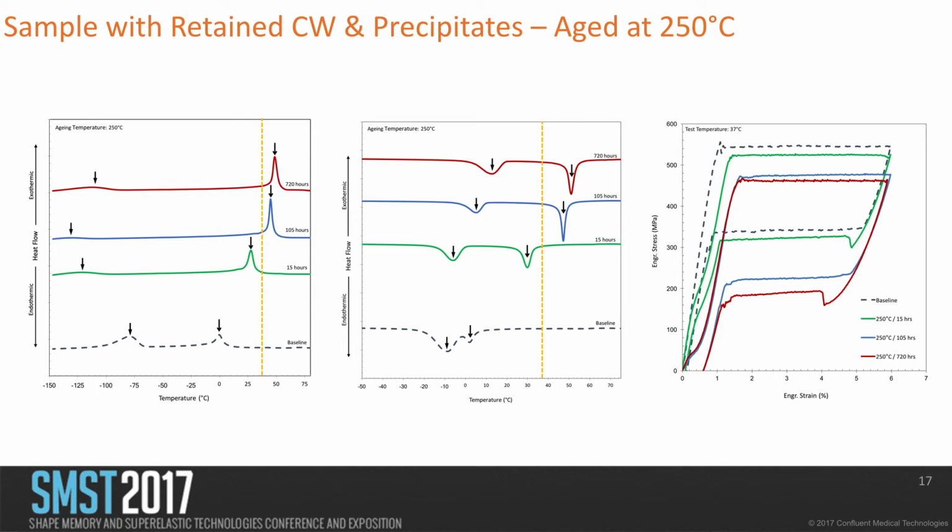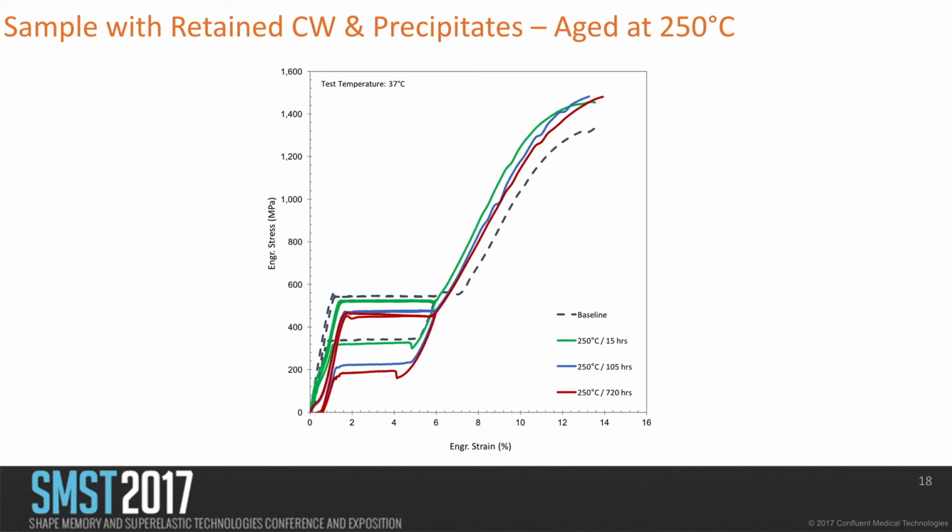Martensite reversion, however, is following the R phase now. Something else is happening in there. And even though we have suppression, the properties drop, which I'll come back to in a moment. And again, just like at 200 C, we have the increase in UTS, some strengthening is happening in the material.